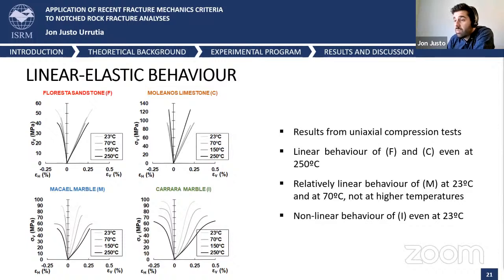The Macael marble also presents quite a linear behavior up to 70 degrees and less linear behavior for higher temperatures. And finally, of course, the Carrara marble does not present a linear behavior even at room temperature. Consequently, worse fracture predictions are expected for this material.